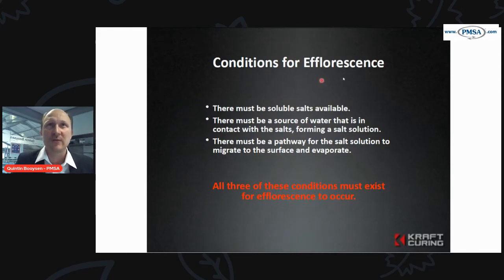So what are the conditions of efflorescence? There must be soluble salts available. Now, in our case, in the concrete, we have the calcium hydroxide, which is in this water. The next one says there must be a source of water in contact with the salts, forming a salt solution. So now we have this product floating in between all the little micro cracks, in between all the capillaries, and that then moves through to the surface. So if there's evaporation, we start getting the salts percolate or moving towards the surface through this capillary action. So there must be a pathway for the salt solution to migrate to the surface and evaporate.